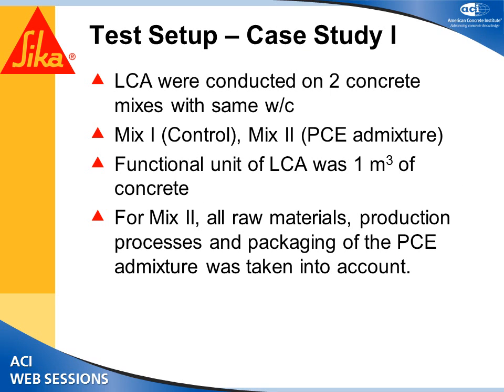So the test setup for this case study was, LCA was conducted on 2 concrete mix designs with the same water cement ratio. Mix 1 was the control and mix 2 was with PCE admixture. The functional unit was 1 meter cube of concrete, and for mix 2, which had the PCE admixture, all the raw materials used in the admixture and the production processes and the packaging were considered and taken into account.